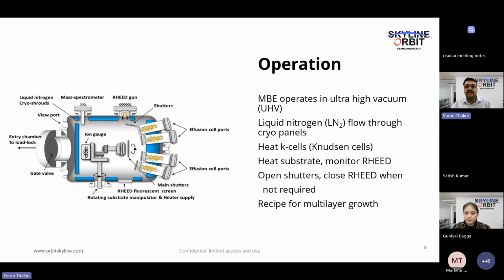The operation basically happens like this: we start with the liquid nitrogen flow. Once the pressure falls to required levels like 10 to the power minus 10, then we start to heat the K cells. The effusion cells are also called Knudsen cells, named after the inventor. When the temperatures are at the evaporation point, we heat the substrate to the growth temperature, and then we monitor RHEED. When the substrate shows features which show atomic cleanliness, we open the shutter. Once the shutter opens, the material reaches the substrate, and we keep rotating the substrate to get a uniform coating. Then we close the RHEED once we don't want to see the growth anymore. And we use a recipe, so the process we can automate. We can feed the recipe in a computer, and that will give us the film as we desire.